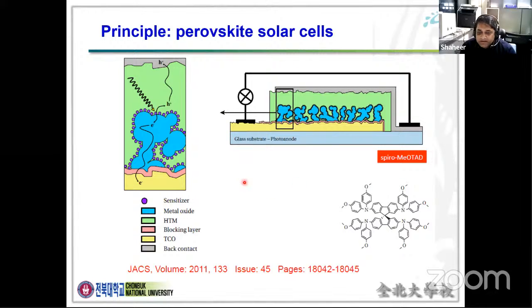So in the reference device, we usually use the mesoporous TiO2 layer, a metal oxide layer, and then the perovskite is the methyl ammonium lead iodide, and then the HTM layer is the spiro-MeOTAD. This kind of spiro material, you can see, this is the spiro-MeOTAD.